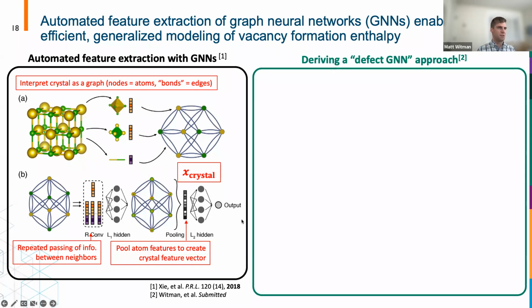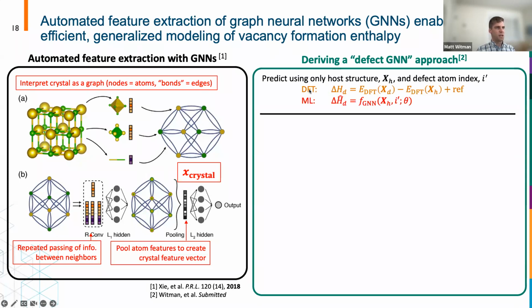So we modified this to be more specific for predicting vacancy formation enthalpies. And so again, I just want to remind you that, when you're doing this with DFT, you have to do N relaxations for every single symmetry site in the crystal. And that's because you have to remove the atom, perform the defect relaxation, measure the energy difference, and that's your relaxed defect formation enthalpy. So what we're proposing with the machine learning model is, can you actually predict that relaxed defect formation enthalpy just knowing the host crystal structure, and then just telling the model which index would be the node that should be defected for the property prediction.